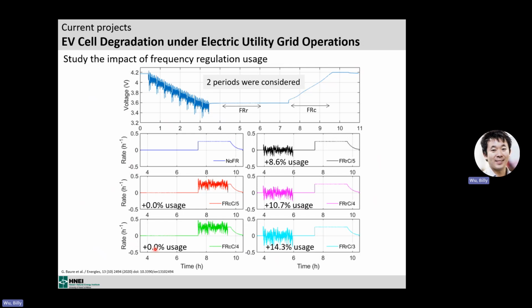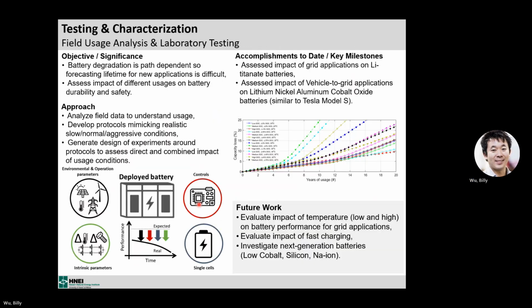So that we could do it without adding any additional usage on the cell, simply by modulating the charge. As you can see here, during the charge, instead of having a constant charge, we just modulate. On average, that's the same current. One with pulses, one not. And for that particular cell, we didn't see any impact, which was really interesting. But under some conditions, the electric grid might be doable for frequency regulation if you modulate the charge. Again, that's published, so if you're interested, please feel free to get the paper.